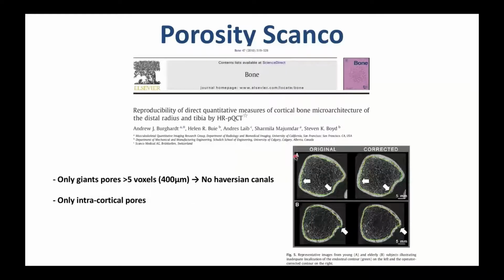So the way the SCANCO machine analyzes porosity has limitations. I'm not going to go into the technical details, but that porosity only captures giant pores, more than 5 voxels, which means around 400 microns, that are not Haversian canals. So all the smaller porosity is not captured by this technique. And also, it only captures intracortical pores.